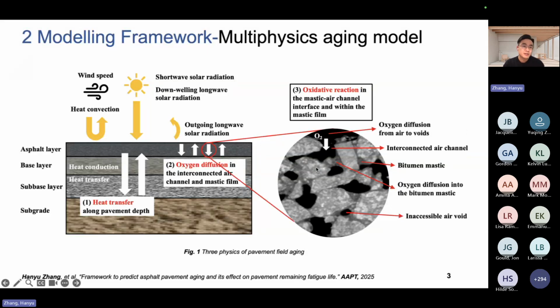So for the modeling framework, I believe most of you are very familiar with aging. So we need to understand the mechanisms for the asphalt aging in the pavement. It is a very typical diffusion and reaction process. Which means that the pavement temperature must suffice to activate this oxidation process. That refers to the first physical process here, heat transfer along the pavement depth. Now we have the temperature. We also need a sufficient amount of oxygen for the oxidation. That refers to the second physical process here, that is oxygen diffusion. Once the temperature and oxygen are ready, the oxidative reaction can happen. That is the third physical process here.